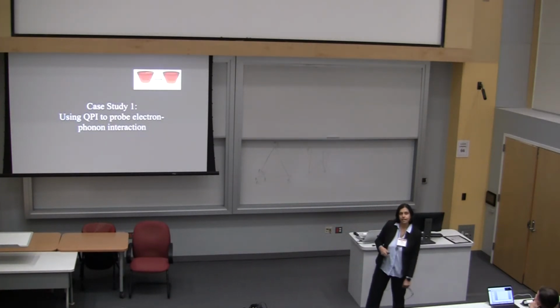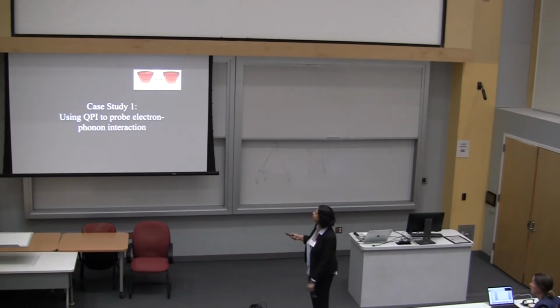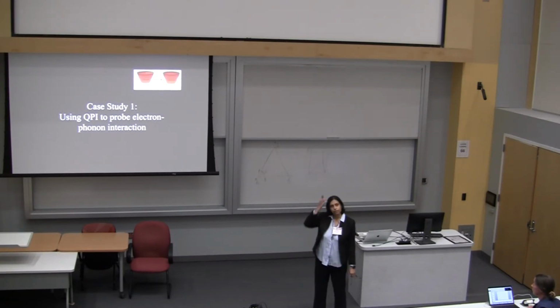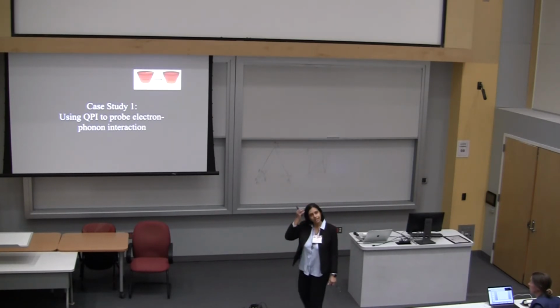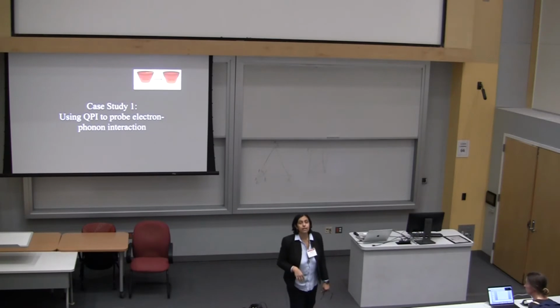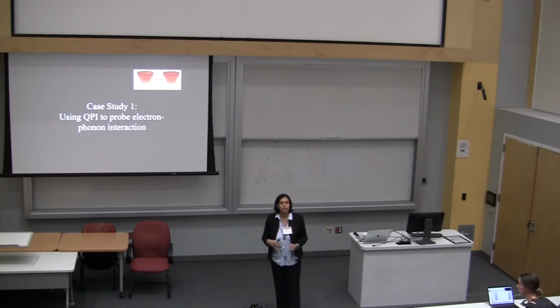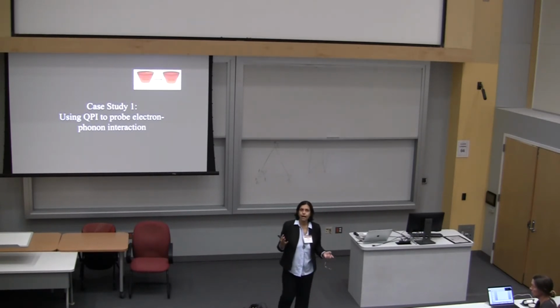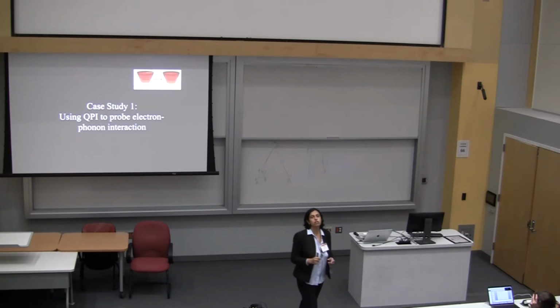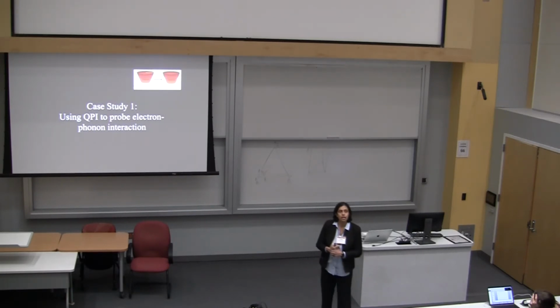So the first case study I want to do is how we can use QPI to probe electron-phonon interactions. The reason I put this first is this is something you might not have seen before. You might have seen you can use QPI to get band structure. That's very common. But the fact that you can actually get quantitative information on electron-phonon interactions, this you may not have seen. So how do you do this?